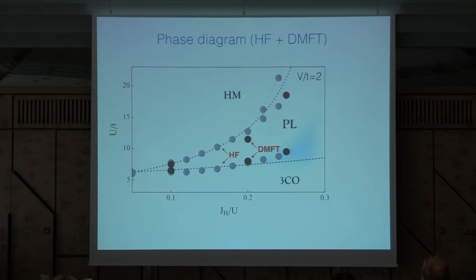So here is the phase diagram. We calculated it by both an unrestricted Hartree-Fock approach, and then we confirmed it by dynamical mean field theory. This is the strength of the local Hubbard term, the local interaction U, and this is the ratio of Hund coupling to U. We have fixed a quite reasonable value of the nearest neighbor repulsion V so that we can get charge ordering. When we start from up here, because we pay a lot of energy if we put two electrons on the same site, we don't want to do this, and the system is homogeneous. There is one electron per site.